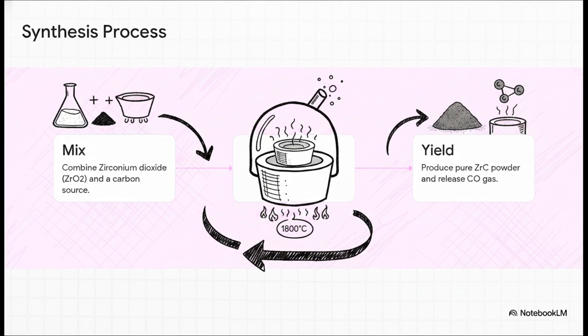Now, researchers emphasize that this requires ridiculously precise control over the heating rate and the vacuum atmosphere to avoid oxygen impurities, because even a tiny bit of unwanted oxygen is a massive performance killer in the final material.